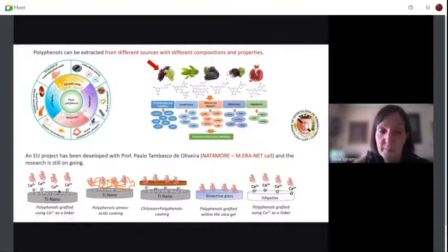But we explored also another chemical treated titanium surface, which has a nanotexturing, but not the deprotonated hydroxyl groups. So in this case, we get the functionalization by using amino acids, and there is a chemical affinity between amino acids and polyphenols. So you can get on the surface a layer of polyphenols entrapped, embedded inside a layer of amino acids. Or we used a chitosan coating on the titanium surface, and we enriched the chitosan coating with polyphenols. And we grafted polyphenols also onto bioactive glasses.